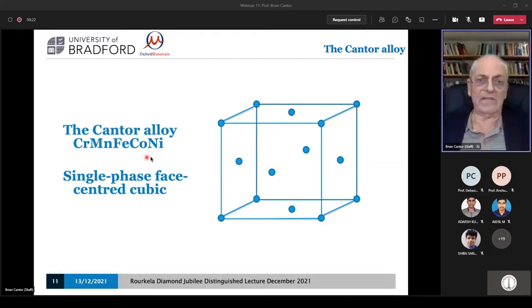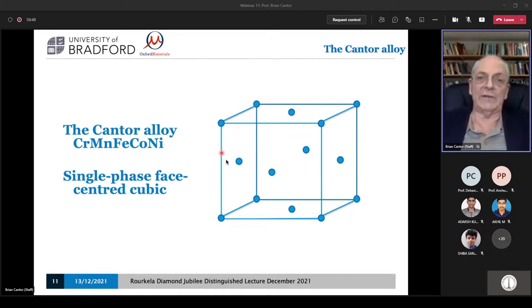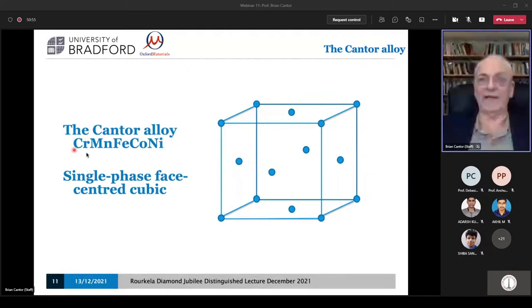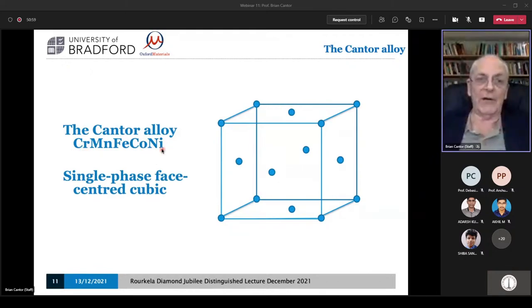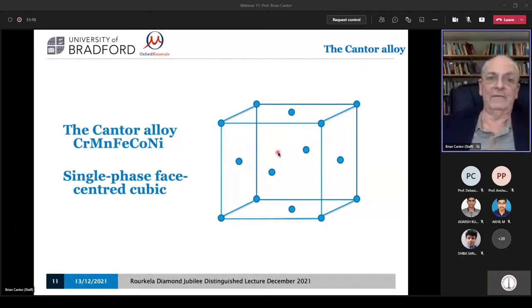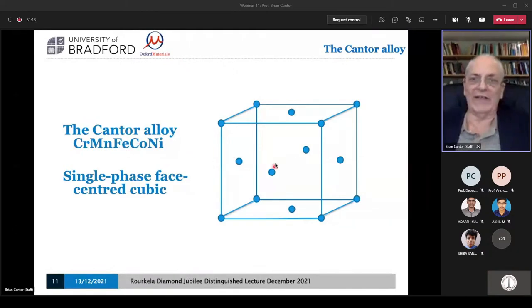Now, this material, the Cantor alloy, consisted of 20% each of these five components, chromium, manganese, iron, cobalt, and nickel, distributed at random with atoms here. So instead of all the atoms being copper, or all the atoms being gold, or all the atoms being aluminium, 20% of them are chromium, 20% manganese, 20% iron, 20% cobalt, 20% nickel, in a disordered random arrangement. Now, nobody could have predicted, nobody did predict that this material could exist. Only one of these five components has face-centered cubic structure, nickel, as its natural structure. And most metals don't mix so much as having five, as far as we knew. We've never tried doing it. It turns out they do mix.